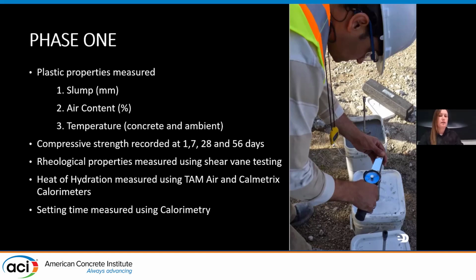Obviously, the common slump, air content, temperature, and compressive strength were measured. And additionally, we measured the rheological properties, the yield stress, shear thickening over increments of 15 minutes for a total period of 1 hour. We were utilizing shear vanes, as you can see in the photo, with the goal of producing mixtures with similar or better properties compared to the baseline shotcrete mixes. We also used calorimetry to understand the heat of hydration and the setting times of a given mix.